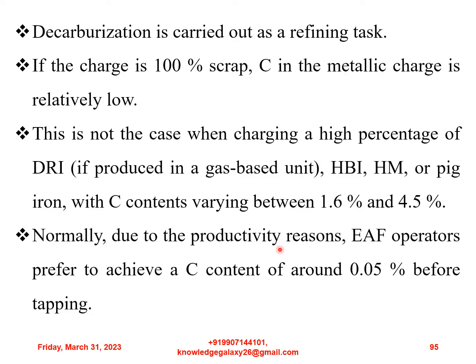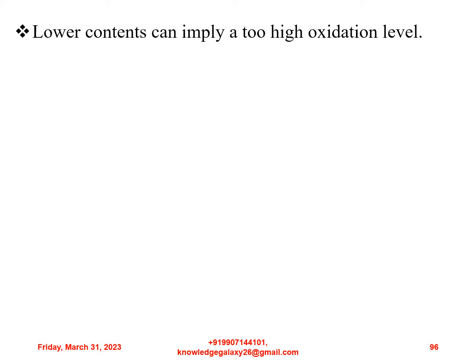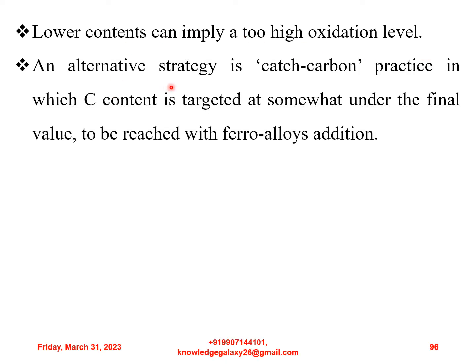Normally, due to productivity reasons, electric arc furnace operators prefer to achieve a carbon content of around 0.05% before tapping. Lower contents can imply a too high oxidation level. An alternative strategy is catch carbon practice, in which carbon content is targeted at somewhat under the final value to be reached with ferroalloys addition.